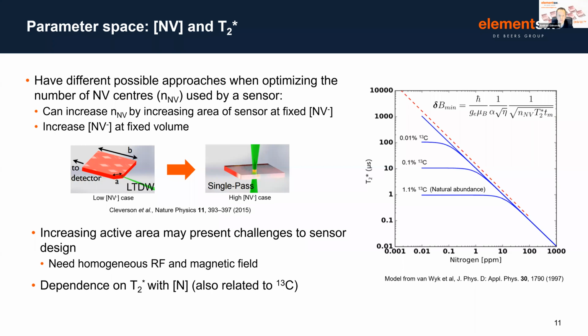Now, these two different approaches are illustrated in this paper from Clevenson, where in the case of a low NV containing diamond, one potentially optimal scheme is to inject a laser into a facet along the side of the diamond sample and then let that laser bounce around multiple times within the diamond sample using total internal reflection.